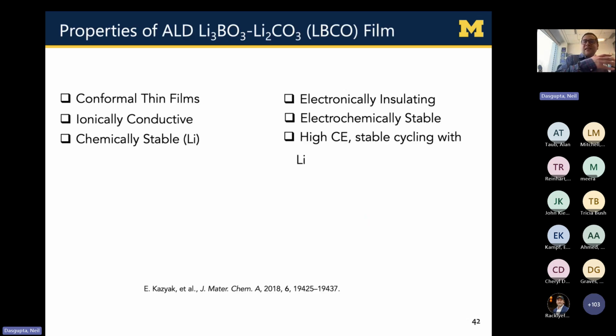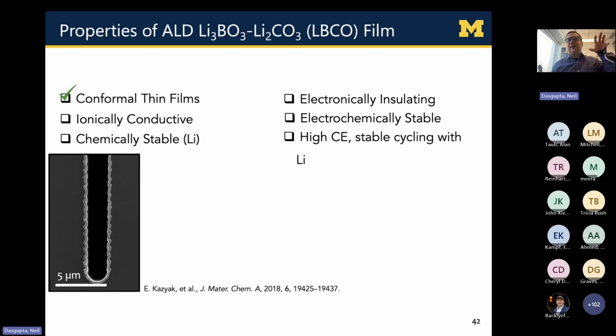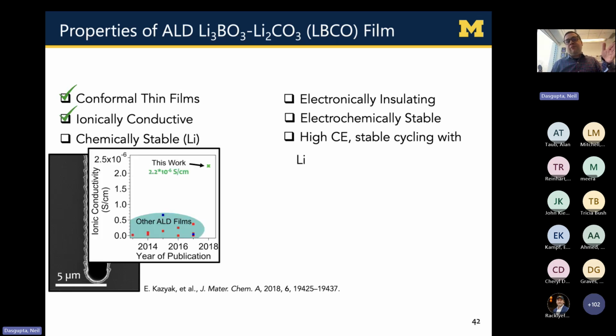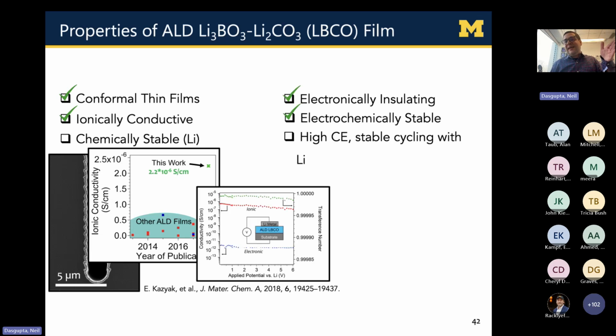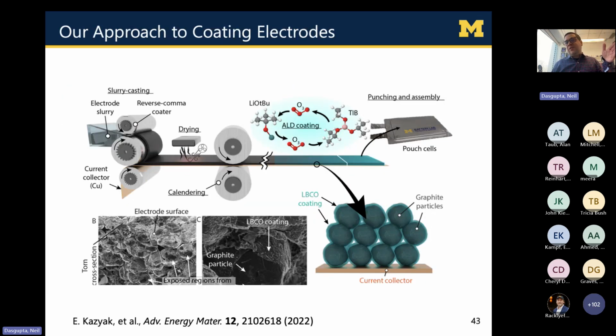Luckily, we've been working on ALD of solid electrolyte materials for the last decade. A lot of that funded through our solid state battery research. We were trying to create optimal, stable, high conductivity interphases in batteries. And we stumbled on this really amazing material, which is a glassy blend of lithium borate and lithium carbonate. We call that LBCO. And we developed this ALD coating process for coating this LBCO that's very conformal. It's got the highest ionic conductivity of any solid electrolyte reported to date by ALD. It's chemically and electrochemically stable against lithium. So we thought, hey, why not try it? What happens if we coat this artificial SEI of this LBCO material onto the graphite? Again, we want to maintain compatibility with current lithium-ion manufacturing. So this is happening continuous after calendering and drying of the electrode.